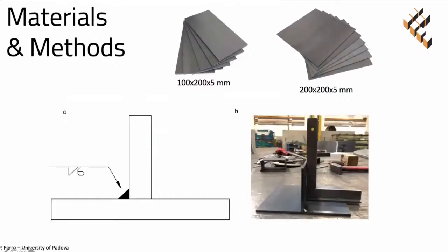by using experimental analysis. Experiments were performed by welding plates of S355 structural steel. The thickness was 5 millimeters, and the geometry of the joint was a T-joint, where we performed only one pass, only one run on one side of these T-joints, in order to introduce a sort of angular distortion that was used to validate the model. So we didn't measure residual stress, we measured the distortion of the joint after welding in order to have a comparison with the numerical results.